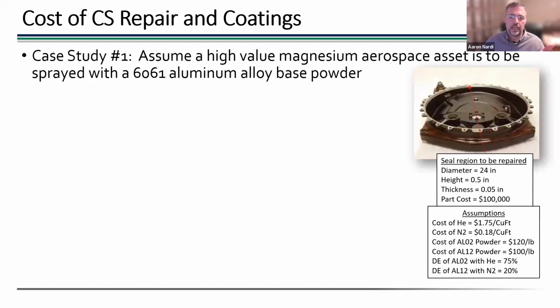So let's look at a simple case study. Take a high value magnesium part, let's say a part with a surface 24 inches in diameter and about a half an inch height, and we want to put 50 thousandths of an inch of material down. Let's say, as an example, this part costs $100,000. I've got the cost of helium, nitrogen, a helium sprayed aluminum powder, a nitrogen sprayed aluminum powder, and the relative DEs of each of those. All those assumptions are here.